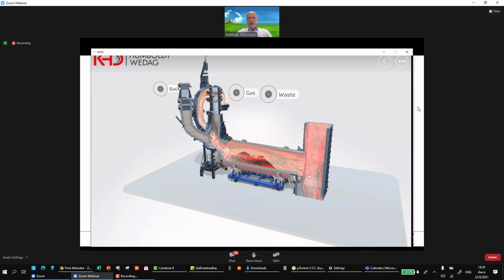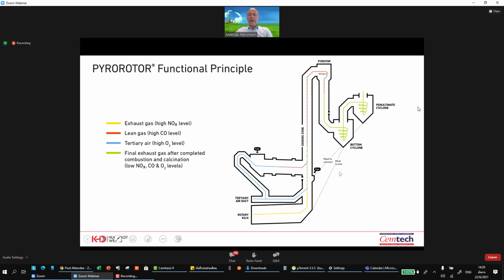in total we have a flow sheet of this system, like to be seen here. We branch off a little bit of tertiary air guided through the pyrorotor. We can set the lambda value according to requirements. We can run the pyrorotor in reducing atmosphere, so to create also a beneficial reducing atmosphere that is reducing the kiln produced NOx as we travel down the calciner into a mixing chamber to have the residual burnout of CO and then come into the preheater with a totally burnt out NOx reduced gas.